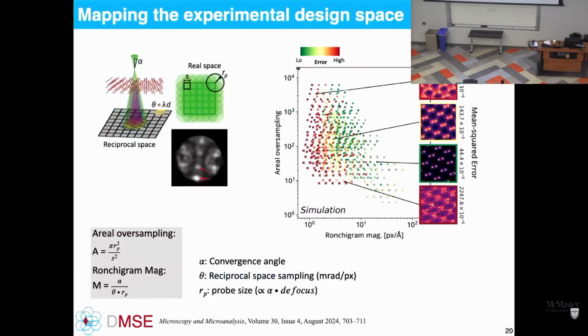And so we spent some time really working out what the optimum parameters were for what we were trying to do, and we developed a couple of parameters that we could use to map out basically the experimental parameters and wrap them up into these: area oversampling, which is basically how much each probe position visits each point on the sample, and the Ronchigram magnification, which is how much information is magnified within that disk that we had illuminated over our sample.